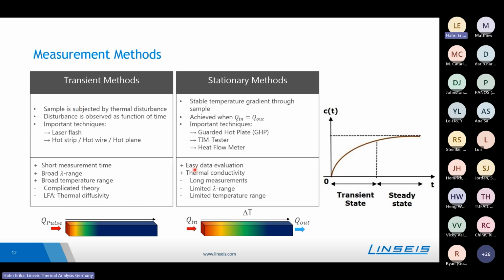For the stationary measurement methods, however, the data evaluation is typically quite easy, and one can directly get the thermal conductivity out of the test. Disadvantages are that one needs to wait until there is a stable state, which might require maybe a couple of minutes or even up to half an hour or 1 hour. The thermal conductivity range is mostly limited, as well as the temperature range is quite limited with the stationary measurement methods.